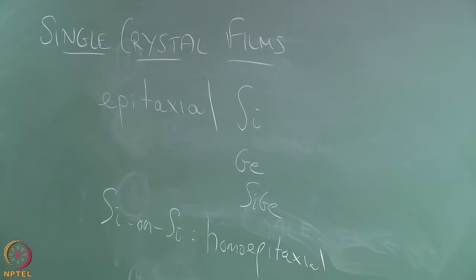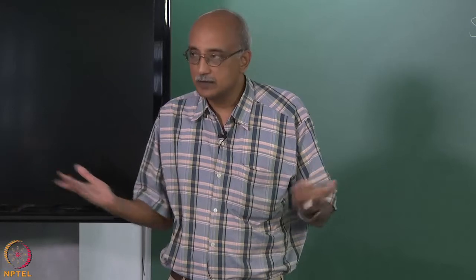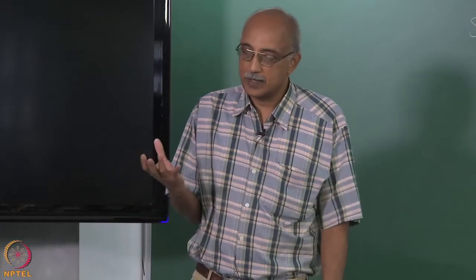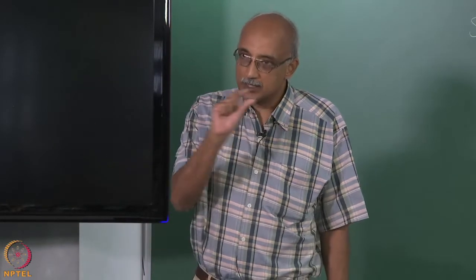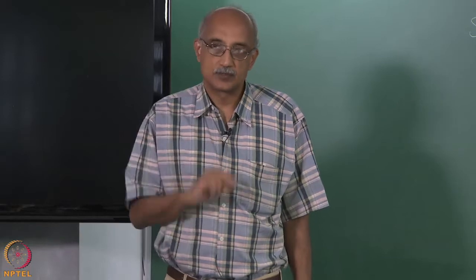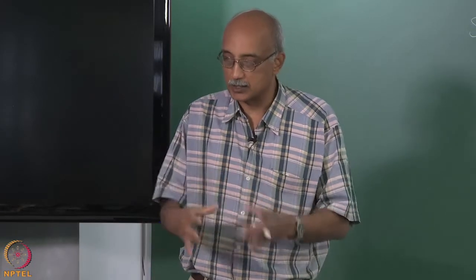Why would you want to do that? I mean, why would you want to put a silicon film on a silicon substrate? What do you gain? The reason you want to do that is bulk silicon that you can get in large quantities has properties that are very difficult to control, widely varying in every possible way. The composition could be varying, the crystalline structures could be varying. So you cannot guarantee that the surface of a bulk silicon ingot has certain properties. But by depositing a very thin film on top of the silicon, you can now have a top layer that has a very precisely controlled crystalline structure sitting on top of this silicon. So essentially you're depositing epitaxial silicon on top of bulk silicon.